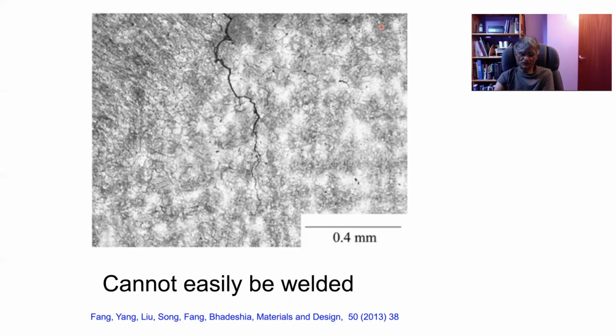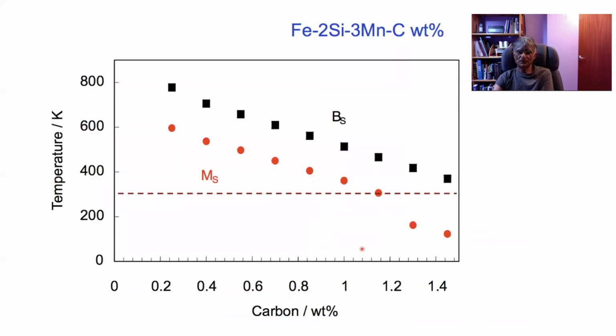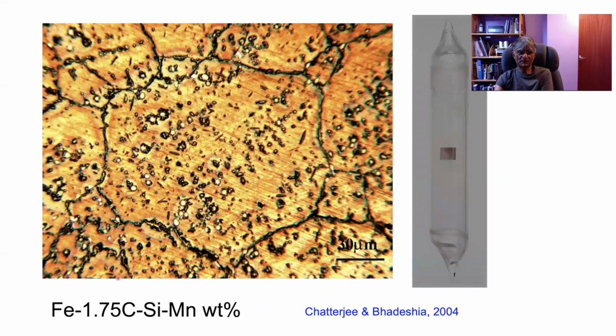But that's another story. Now, I mentioned to you that if you have this sort of a carbon concentration, then it's going to take 100 years to produce bainite. But we nevertheless made this material. Okay, so this material has 1.75 weight% carbon, and similar manganese and silicon concentrations, and it looks like this. And it ought to transform at room temperature in 100 years.